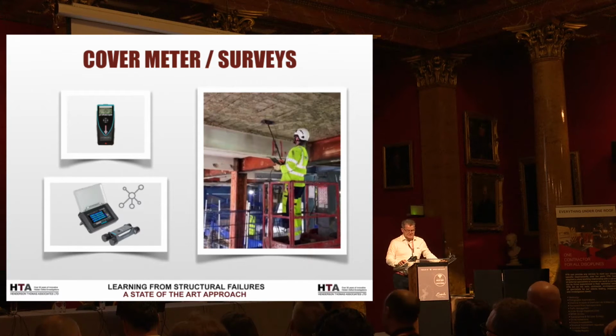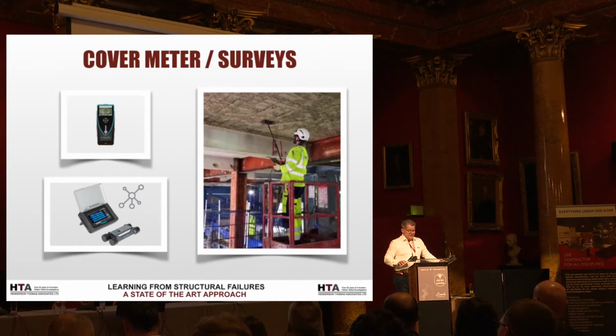One of the things I must state here is there's a lot of misinformation to do with cover meters. If you want to accurately determine the size of a reinforcing bar in concrete, you have to break it out and look at it and then use the cover meter to calibrate the readings and see if that varies elsewhere on the structure. There are a number of companies who purport that you can just use their cover meter and you don't need to break out. Completely false. So if you are needing to do an assessment of a structure and accurately determine the bar size, and in some instances the bar type, you have to break it out. Anyone tells you you don't, it's incorrect.